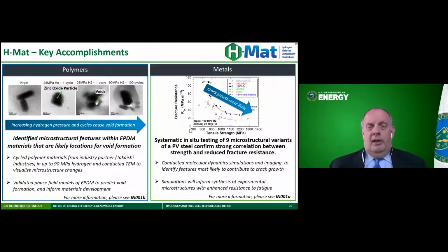Similarly with metals, this is an example where they took 9 different microstructural variants of a single pressure vessel steel, and they're able to do a correlation and understand the relationship of the microstructure, the strength and the other properties of the material with its fracture resistance. Using this, they're able to identify ways to improve the production of the materials, for instance the heat treatment and the annealing temperatures, to get better performance. And so we can get longer life and hopefully lower cost from these materials used in service.